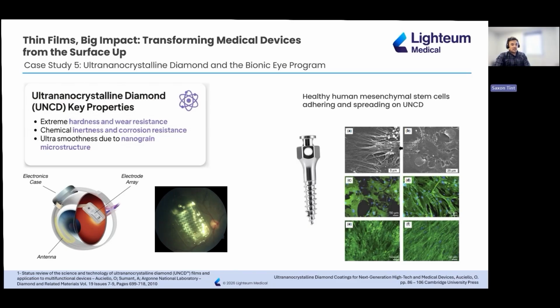One striking example comes from the work done by Professor Orlando Auciello and collaborators at the Argonne National Laboratory. They used UNCD to encapsulate silicon retinal implants. This ended up becoming the Argus Bionic Eye program. The UNCD coating reduced electrical leakage by over 2 orders of magnitude compared to bare silicon, while forming a pinhole-free biocompatible layer. They found that when they implanted this into a rabbit eye for months, there was no inflammatory response.